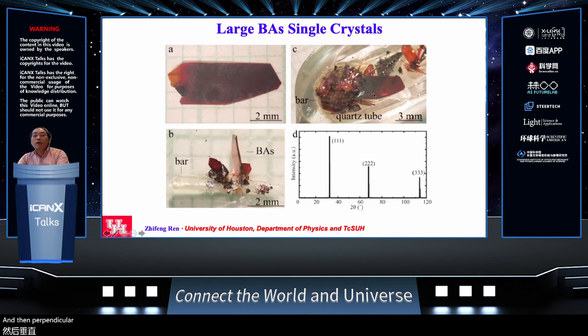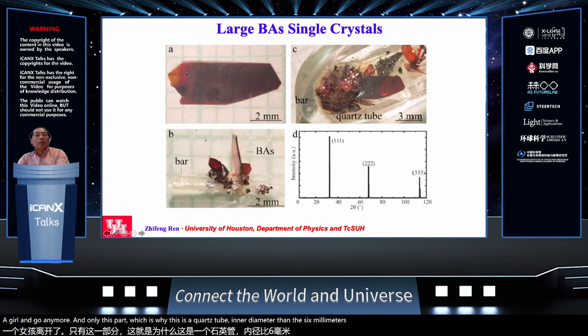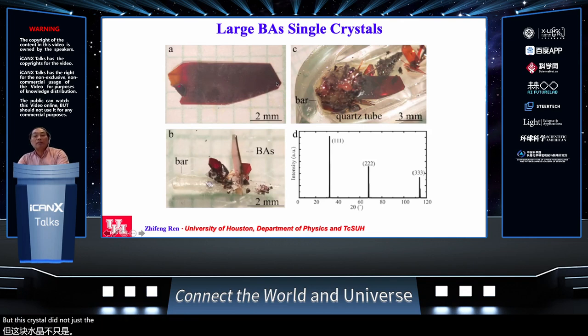a perpendicular bar grows. And when it touches the quartz tube, it cannot grow anymore, and only this part grows, which is why this quartz tube inner diameter is only 6 millimeters, but the longest dimension of this crystal is 7 millimeters. So we found some crystal growth mechanism, and this is obviously also a single crystal.